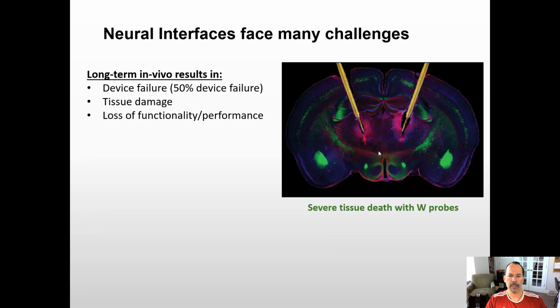So looking at some of the old data, this is tissue histology from the brain of an animal, now about a decade old. These are tungsten probes showing where the deep brain stimulation probes were, and we're seeing a lot of damage in this particular animal, both inflammation surrounding where the probe was and a loss of neural tissue where the probe was. So long-term in vivo results that are out there, at least until recently, unless there's something new that I'm not aware of, have shown a big problem with about 50% device failure over time, meaning that half of the implants stop working, sometimes very quickly during the acute phase and oftentimes during the chronic phase. There's tissue damage and there's a loss of functionality and performance.